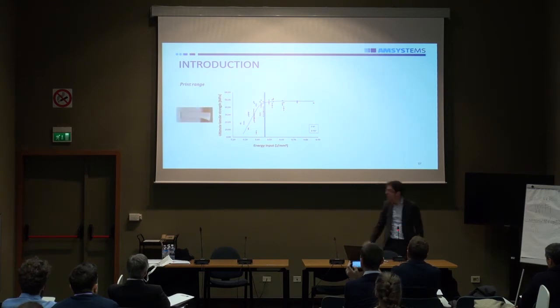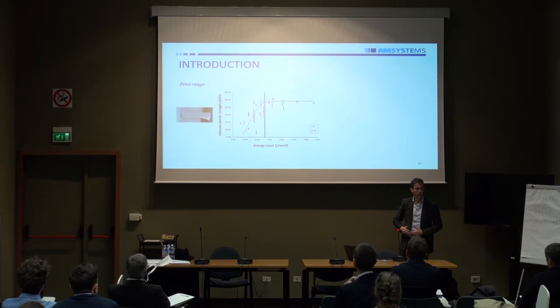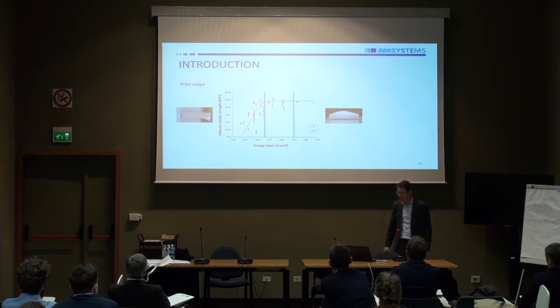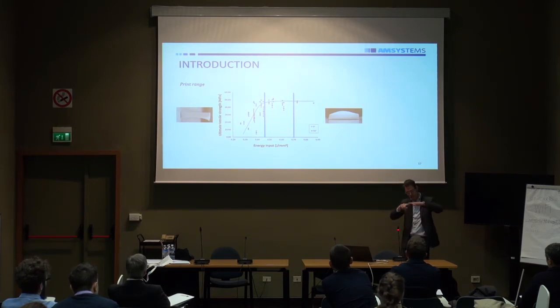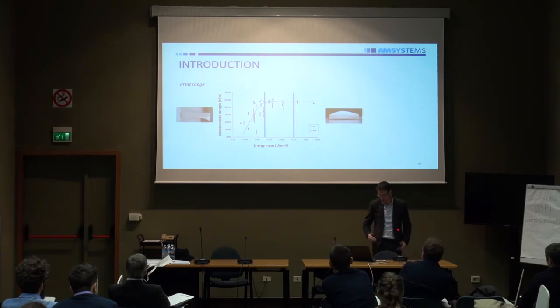So if you put it very low, you see this delamination. So that's not good. But also, if you make it very high, you can see, I think it's upside down, so upside down, you can have a lot of extra melt of material on your product. So that's also not wanted. So what you would want is to stay in your optimum process window. And now everything is kind of open loop. So you just hope it doesn't shift too much.